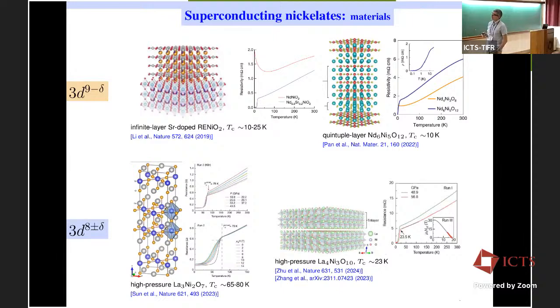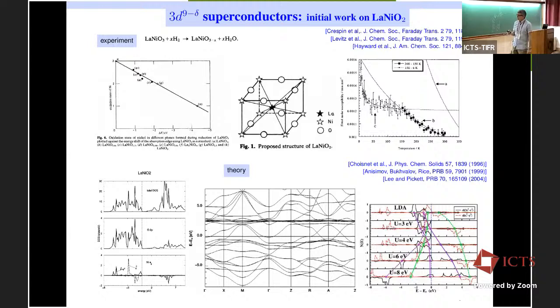First, let's tackle this infinite layer system that was found first by the Stanford group and then continued also by Mundy's group and so on. So there's been a long story, as people thought very early on to characterize this infinite layer. So what does infinite layer mean in this case? It means something specific, namely that you take out the apical oxygen in your octahedron that would form around the transition metal site.